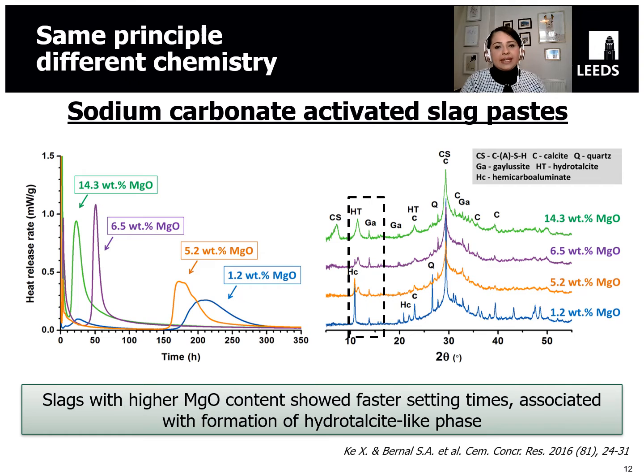So once again, with the fantastic Xinyuan Qi, this is the work during her PhD, we started looking at different slags and activated them with sodium carbonate. And once again, we identified that there was some sort of correlation between the slag composition, particularly the magnesium oxide content, the kinetics of reaction of these cements, and of course the phase assemblage evolution of these cements as well.